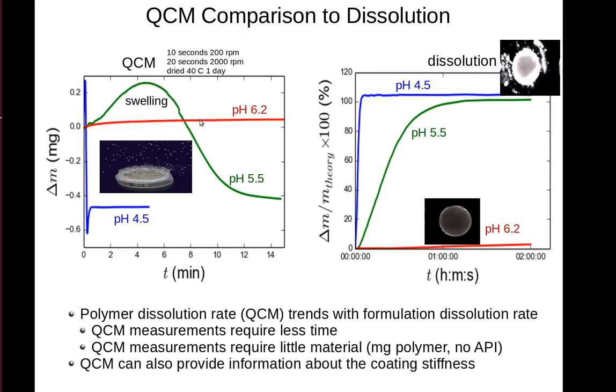Conversely, at a pH of 6.2, there is some minor swelling, but no apparent dissolution. And finally, at the intermediate pH of 5.5, there's swelling followed by dissolution of the polymer.